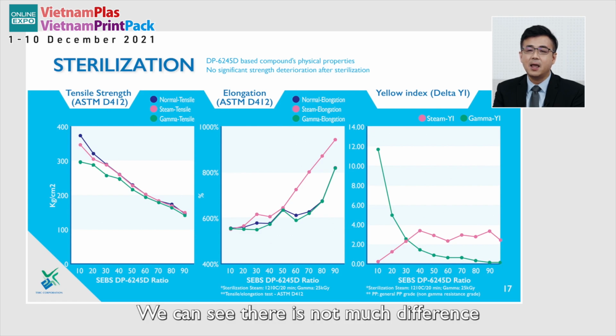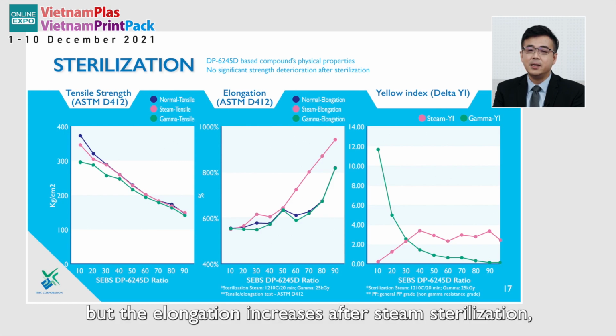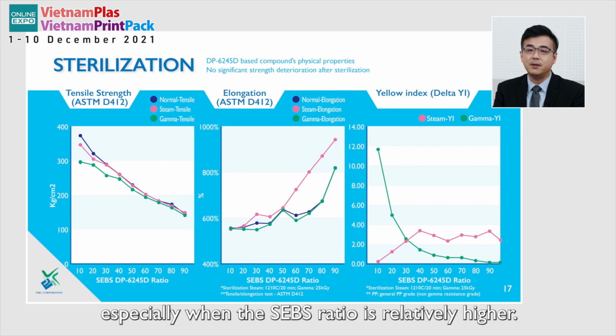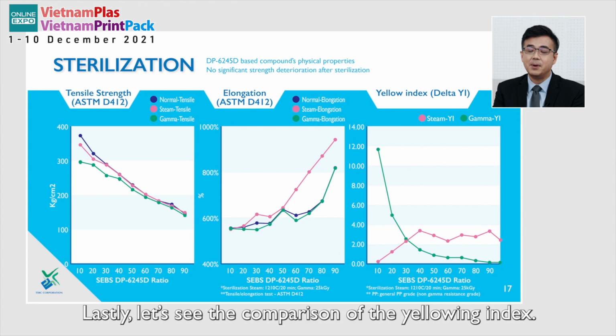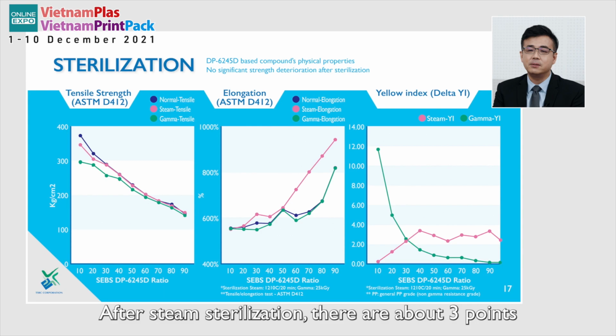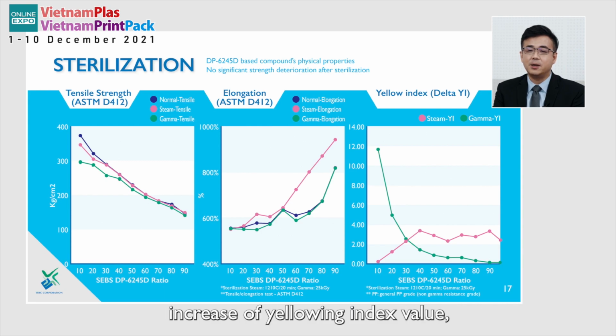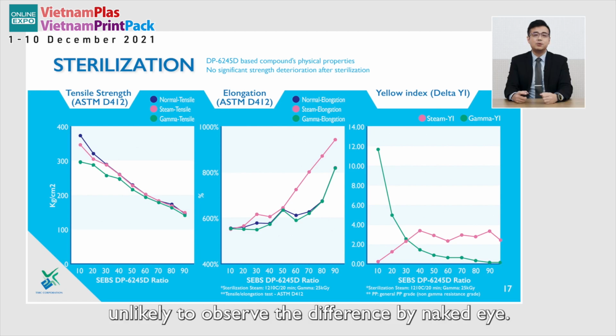We can see there is not much difference after gamma sterilization, but the elongation increases after steam sterilization, especially when the SEBS ratio is relatively higher. Lastly, let's see the comparison of the yellowing index. After steam sterilization, there is about a 3 point increase of the yellowing index value, but the difference is not obvious. It is unlikely to observe the difference by naked eye.